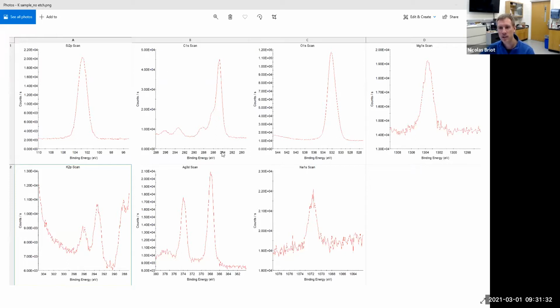But as I was just mentioning, XPS is so surface sensitive that you capture a lot of surface contamination. So what you often do is clean the surface a little bit. In our system, we can use an argon ion beam and just raster it at the surface to erode, to mill the sample a little bit to get rid of that surface contamination. And then you see what's below. So I run the sample a second time, this time after 30 seconds of etching it.